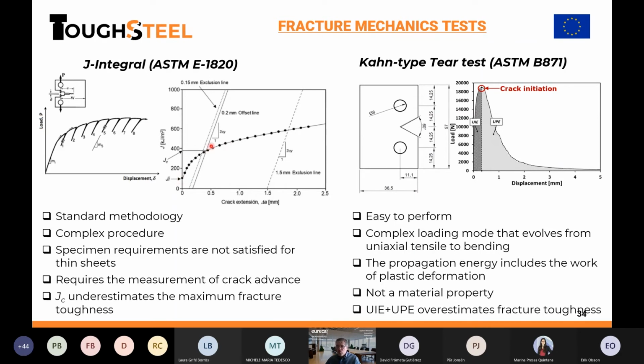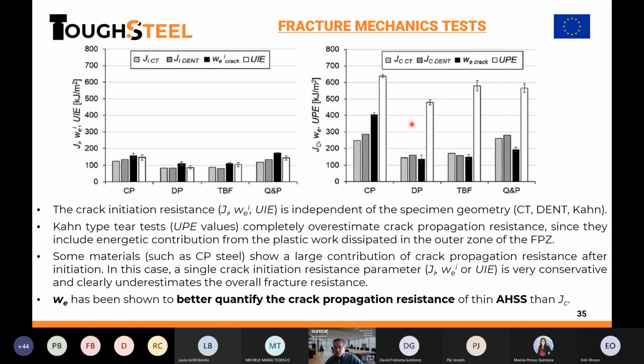But the extent of the energy use increases, because the more we open the crack tip, the more compression and bending we have on the other part of the crack. So this total energy is not really clear. The standard suggests using this, and this value can work sometimes, but sometimes not. We will see this. The Kahn-type tear test is similar. We can also estimate the initiation, but again, the values we get from these parameters, from the energy of initiation and propagation, overestimate fracture toughness, mostly because the crack is not growing in a similar tension mode.